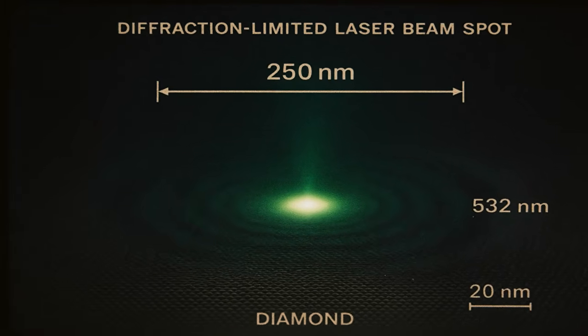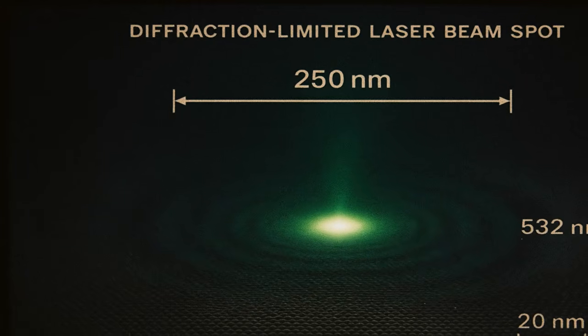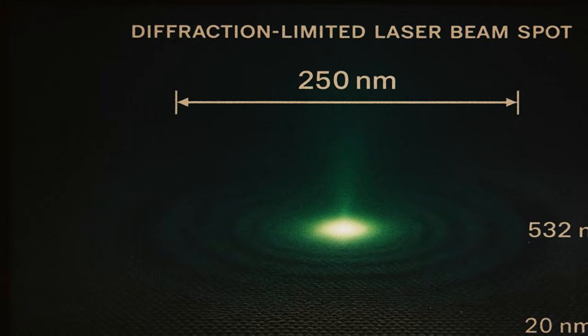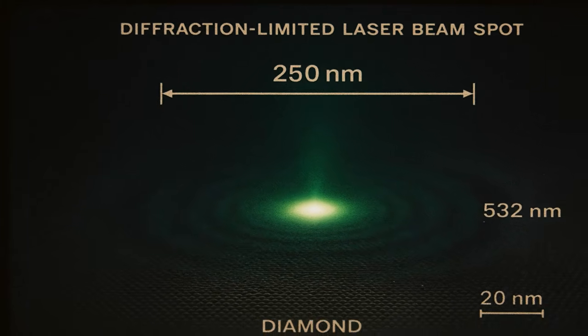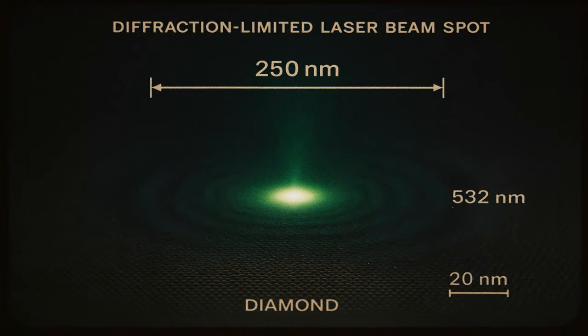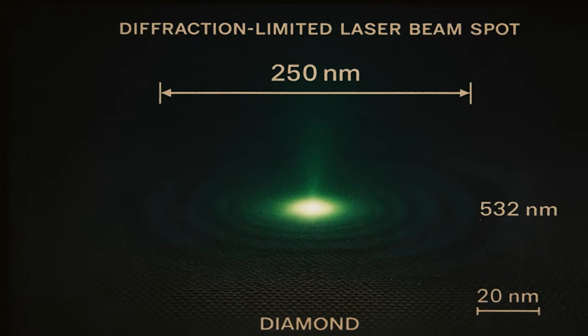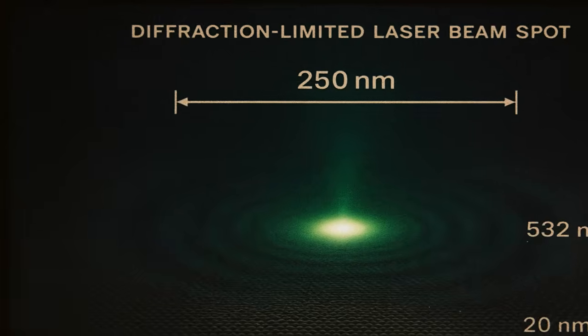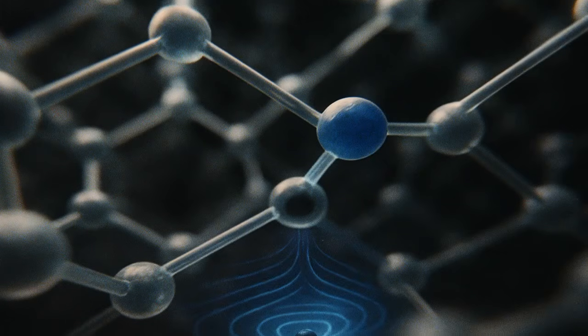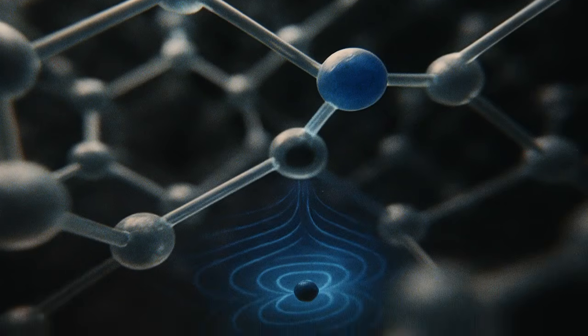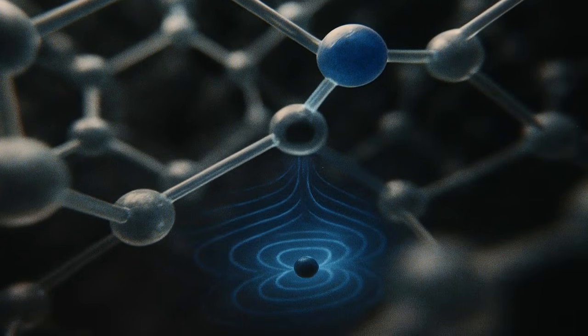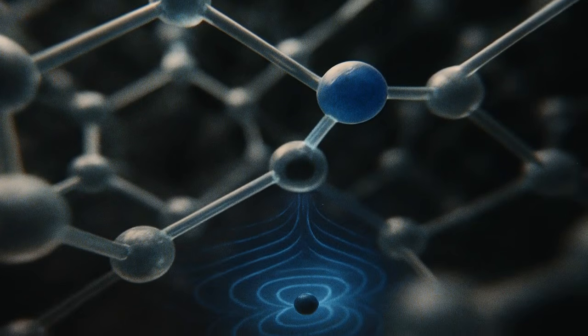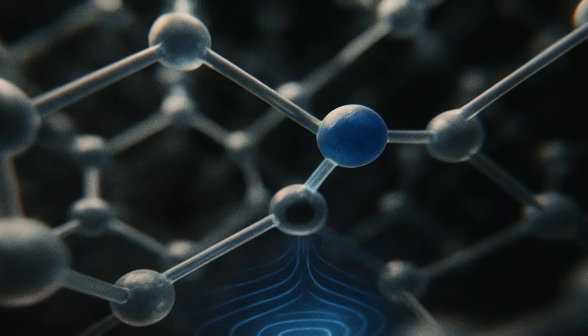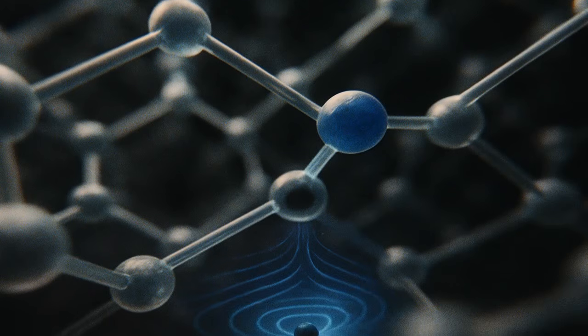Once initialized, apply microwave radiation at 2.87 gigahertz. That's resonant with the 0 to plus 1 transition. The spin flips. Now the NV center is in M sub s equals plus 1. Optically, read out the state by measuring fluorescence. M sub s equals 0 is bright. M sub s equals plus or minus 1 is dim. You've just measured the spin state using light. That's optically detected magnetic resonance, invented for NV centers in the 1990s.